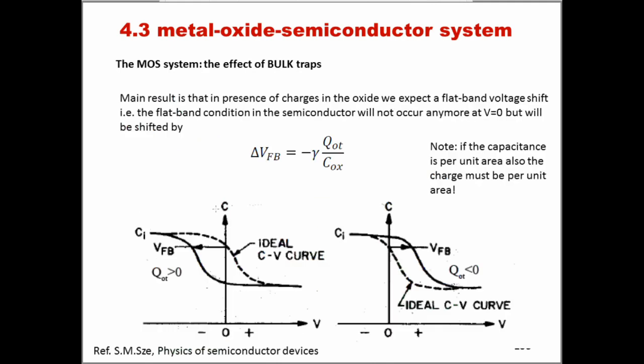So all this is telling us that in presence of bulk traps, bulk charges in my MOS system, I should expect a shift in the flatband condition. And so this is going to shift my CV curve, as I've shown in these two plots, to highlight what happens when the oxide trapped charge is positive or when the oxide trapped charge is negative. So in this case, the shift is toward the negative side of the voltage axis, while in this case here, the shift is toward the positive side of the axis. This is still, remember, for the case of a P-type semiconductor.